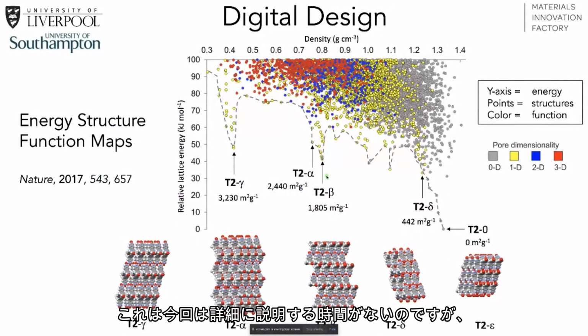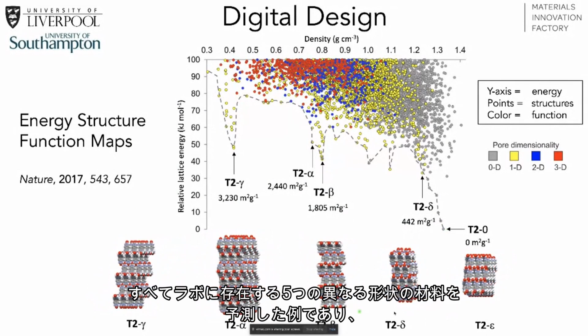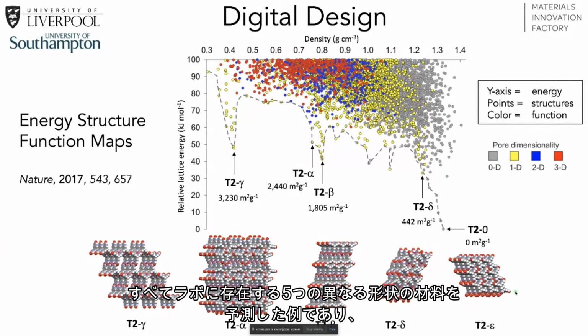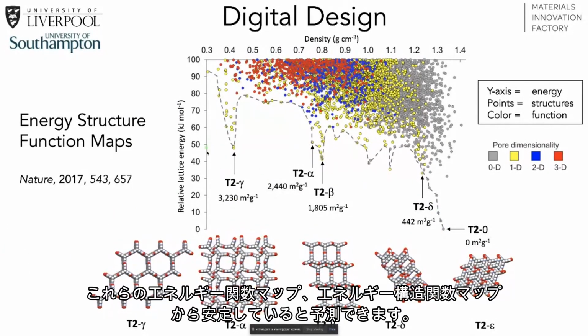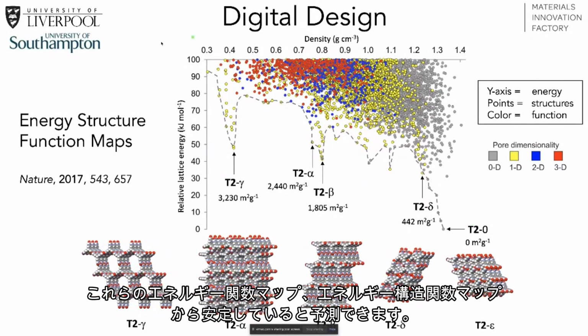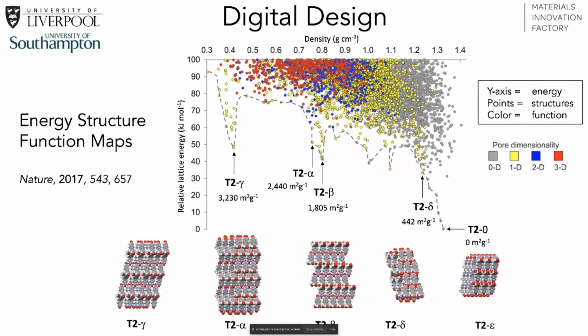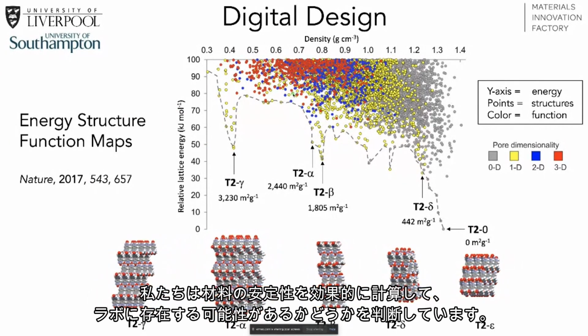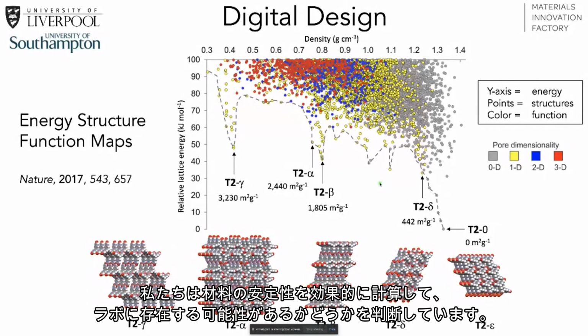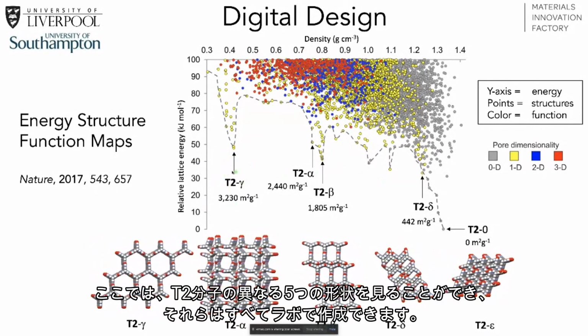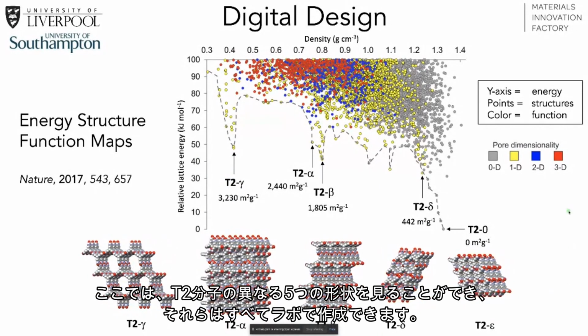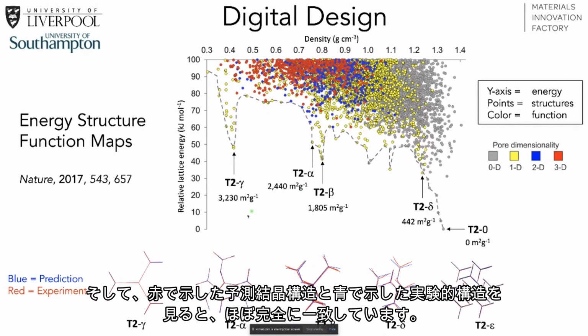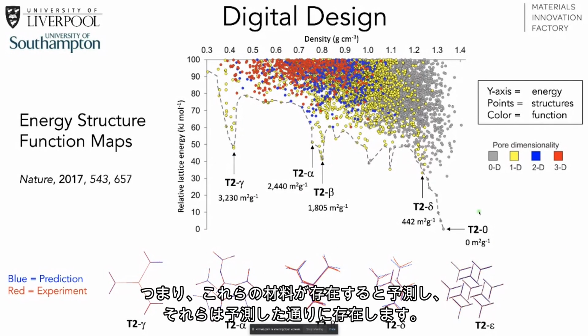And this gives an example, which I don't have time to go into the details, where we predicted 5 different forms of a material, all of which exist in the lab and can be predicted as being stable from these energy structure function maps, where effectively we're calculating the stability of the material to determine whether it's likely to exist in the lab. And here we find 5 different forms of this molecule T2, and they could all be made in the lab. And if you look at the agreement between the predicted crystal structures in blue and the experimental structures in red, you get an almost perfect agreement. So we predict that these materials will exist, they do, and they exist exactly as predicted.